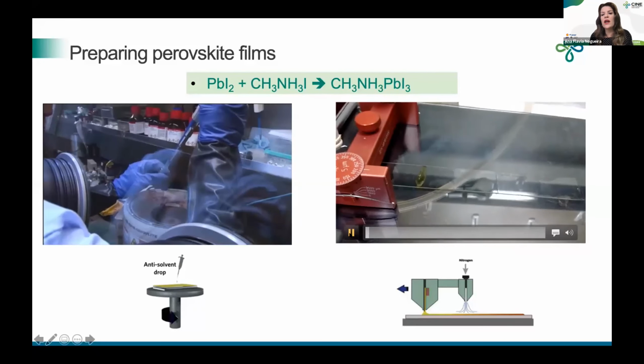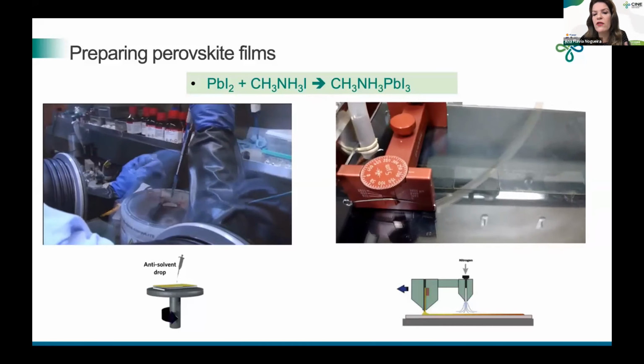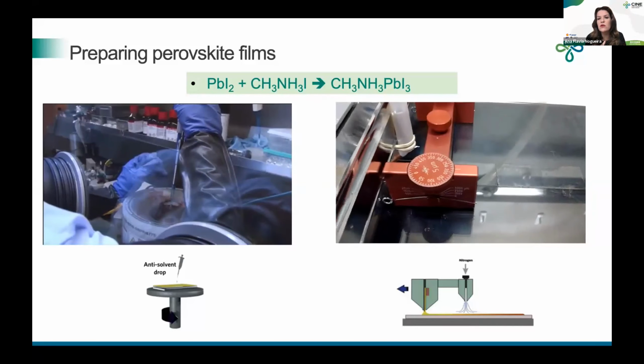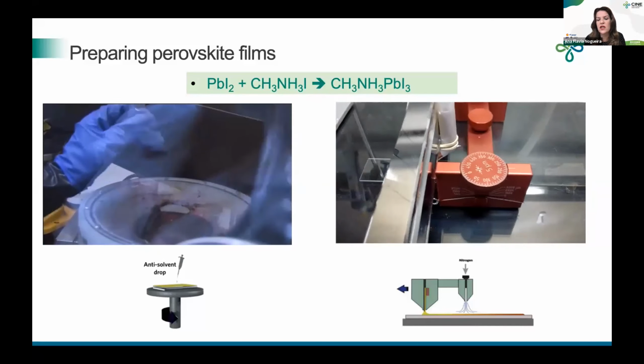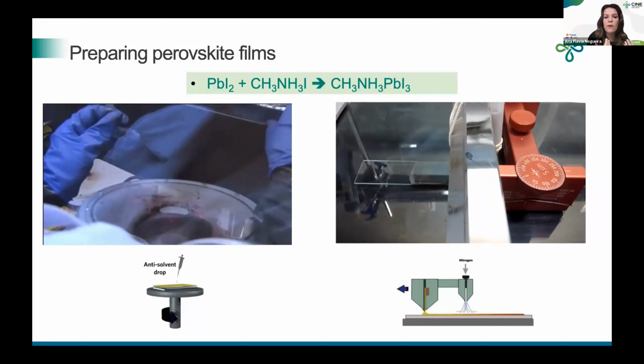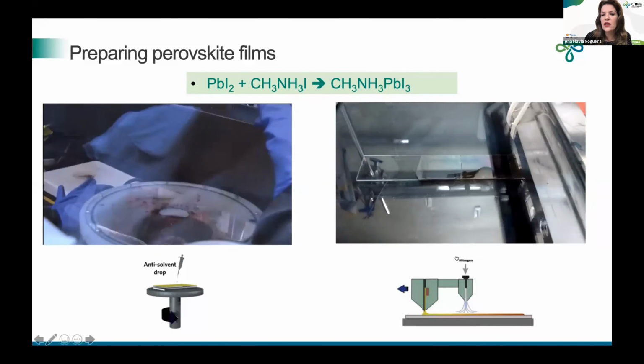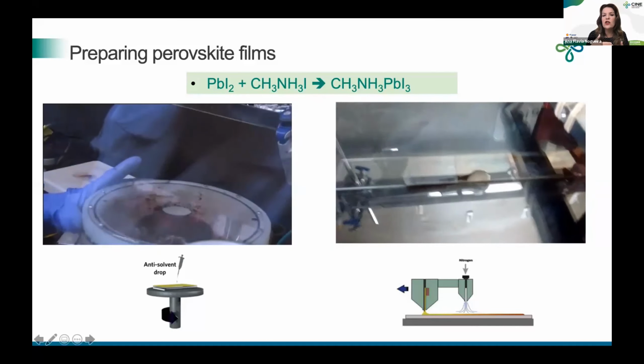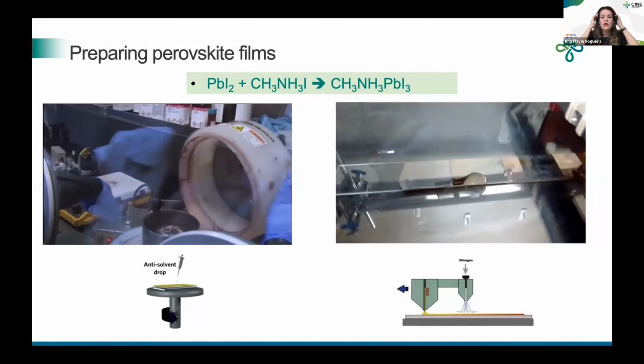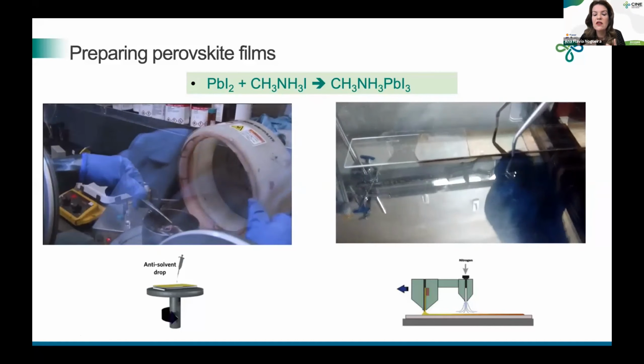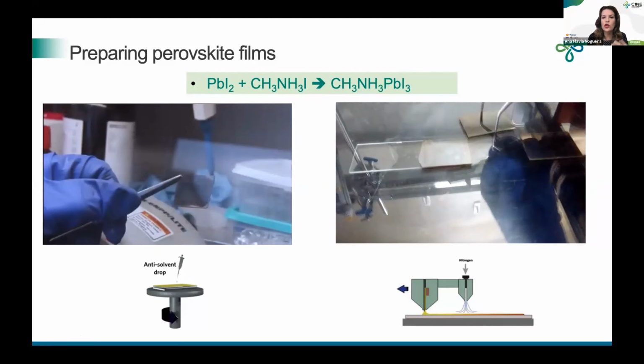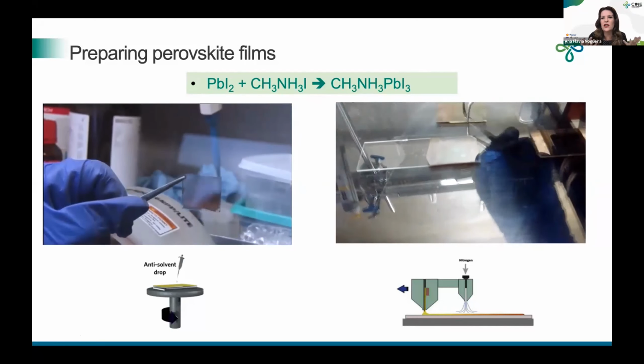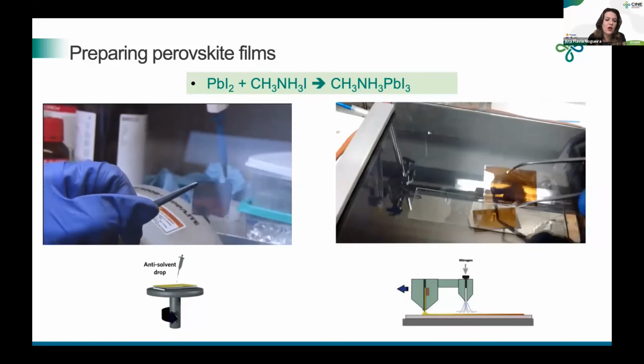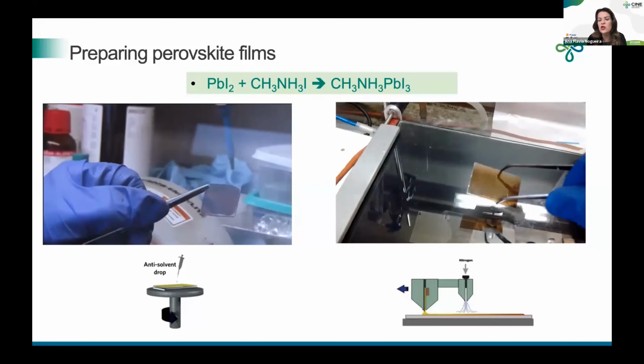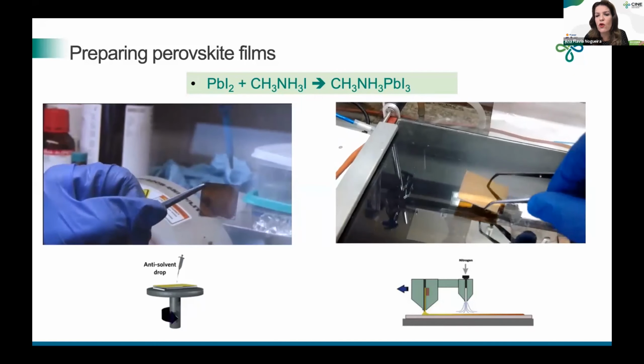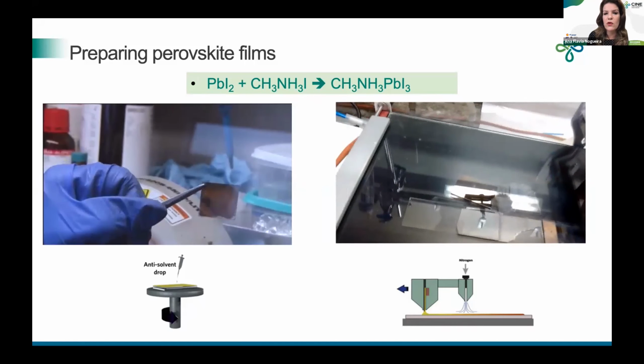The method here on the right is much more scalable. Here you also have the precursor solution, but it is called a blade coating process. You spread your film, and instead of dropping the anti-solvent, you have a flux of nitrogen on the head of the knife that is actually crystallizing the perovskites. As you can see, the method on the right excludes toxic solvent. You do not pollute your glove box, because you do not saturate its atmosphere. So it also allows us to go, for instance, for large area. But in both cases, of course, you can have really nice perovskite films being formed.